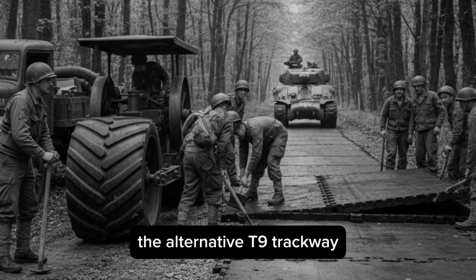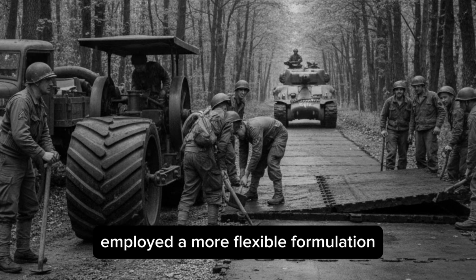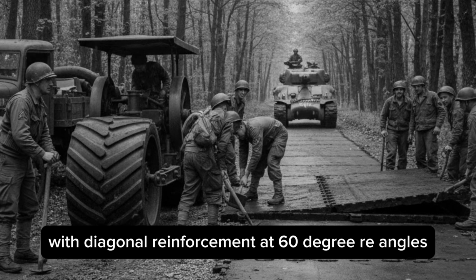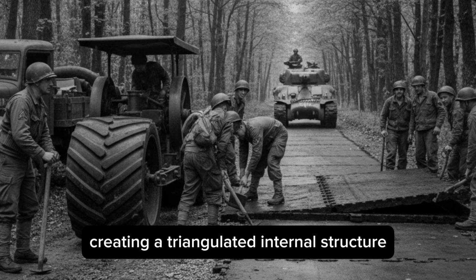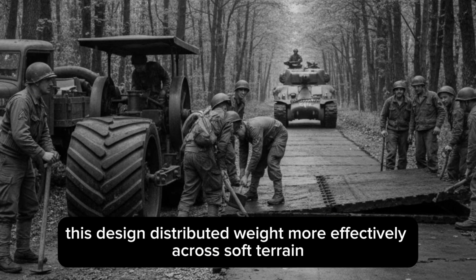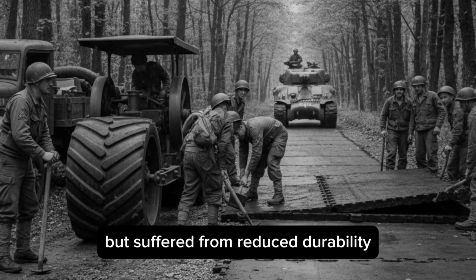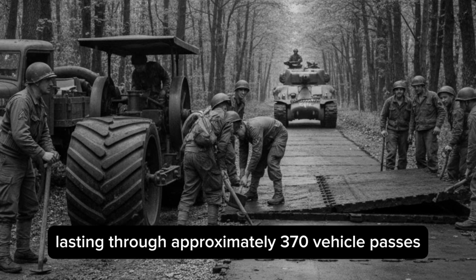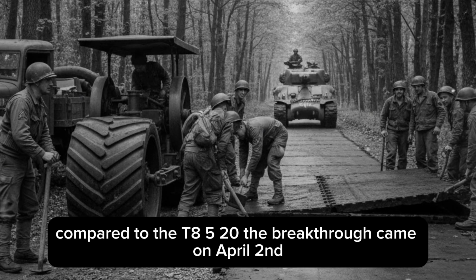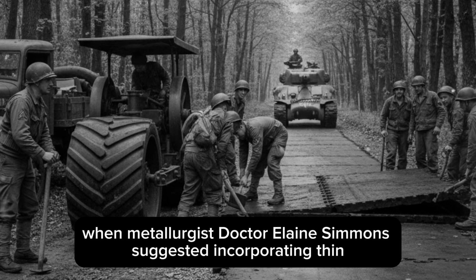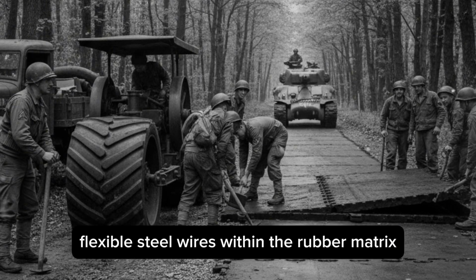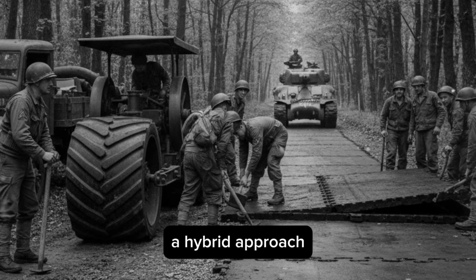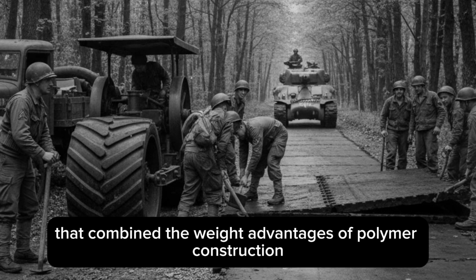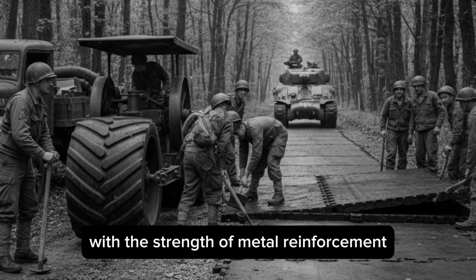The alternative T9 trackway employed a more flexible formulation with diagonal reinforcement at 60-degree angles, creating a triangulated internal structure. This design distributed weight more effectively across soft terrain, but suffered from reduced durability, lasting through approximately 370 vehicle passes compared to the T8's 520. The breakthrough came on April 2nd, when metallurgist Dr. Elaine Simmons suggested incorporating thin, flexible steel wires within the rubber matrix, a hybrid approach that combined the weight advantages of polymer construction with the strength of metal reinforcement.